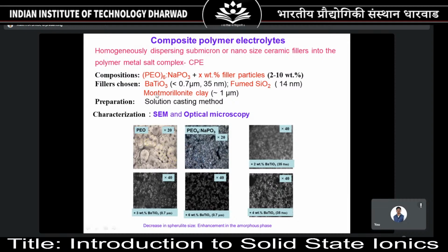So here we have chosen barium titanate of different sizes, 0.7 microns and 35 nanometer. And when it comes to the silica, it is about 14 nanometer. And there are some clays, kind of montmorillonite clays and other ceramic materials or fillers. You disperse these materials into the polymer, and you can look at the optical microscopy, how it has changed. These images, the first 2 images, I have already shown you in the previous case of the sodium metaphosphate based polymer electrolyte.